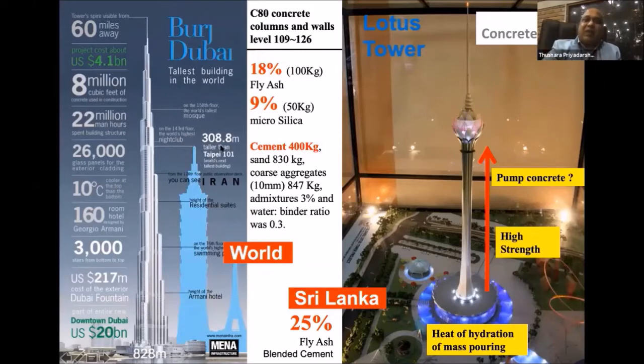So they have used 10 millimeter aggregate. Of course, very high amount of admixtures. This is quite high. In Sri Lanka, usually it's around 1%. And water binder ratio is 0.3. So this is where actually we need to move. We need to use these high performance concrete designs.